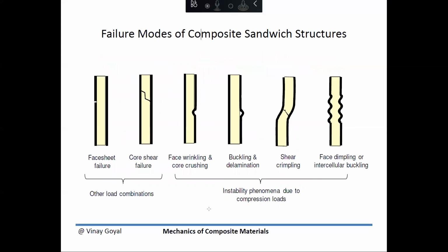The failure modes of composite sandwich structures need to be discussed. We can have face sheet failure in this manner. We can have core shear failure in this manner, so the core cracks in this manner. You can have face sheet wrinkling or core crushing. You can have buckling or delamination. If you have a debond between the face sheet and the core, it can cause this kind of delamination, and it can pop the face sheet or break the fibers. You also have this misalignment situation that can lead to a shear crimping type of failure mode.